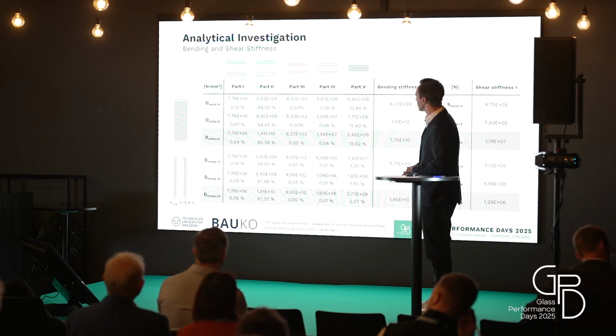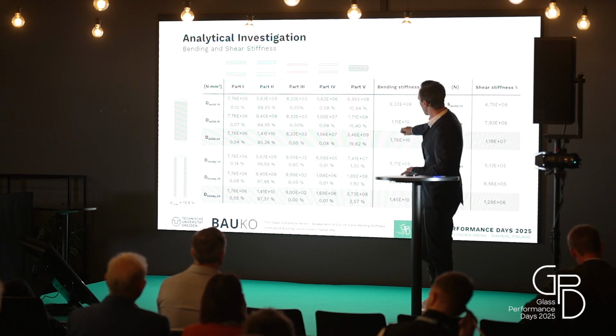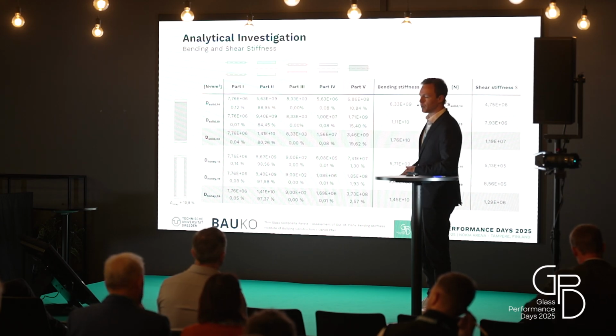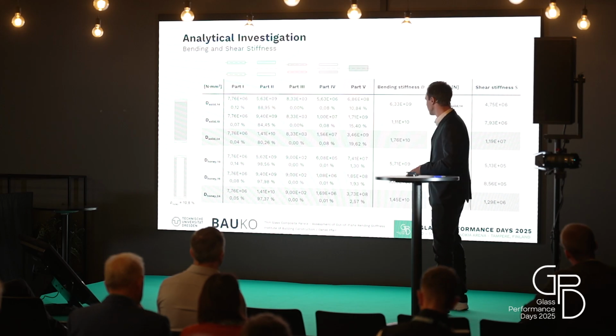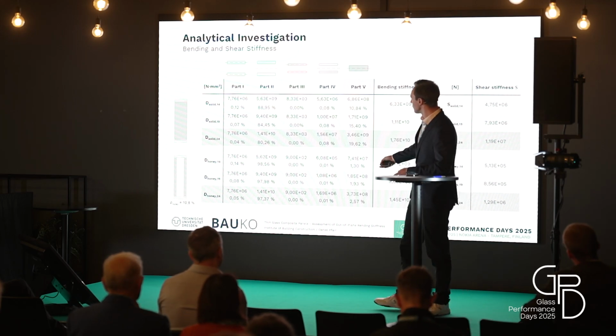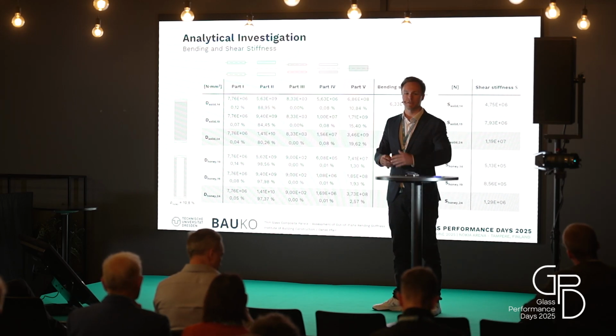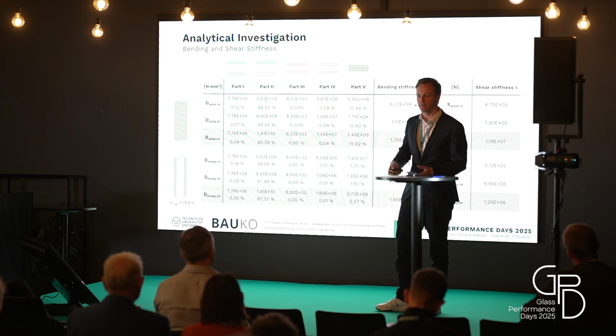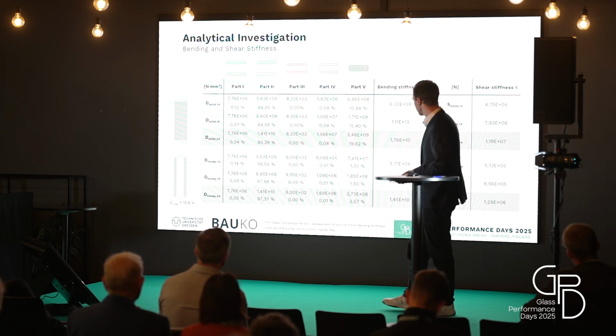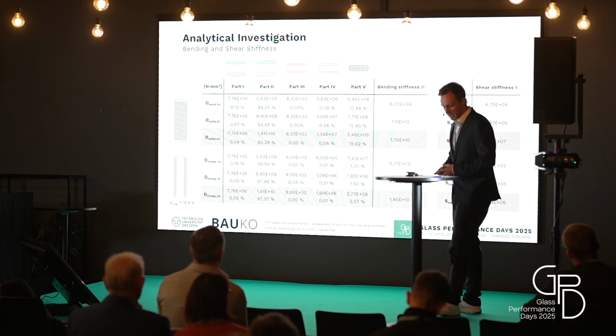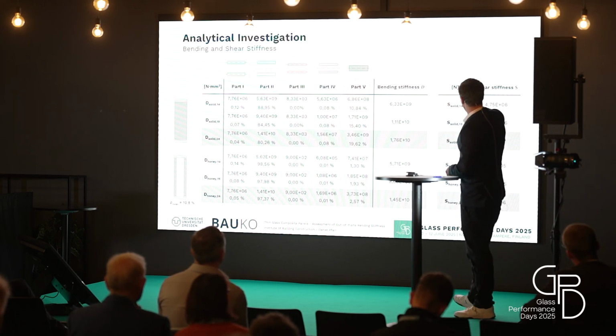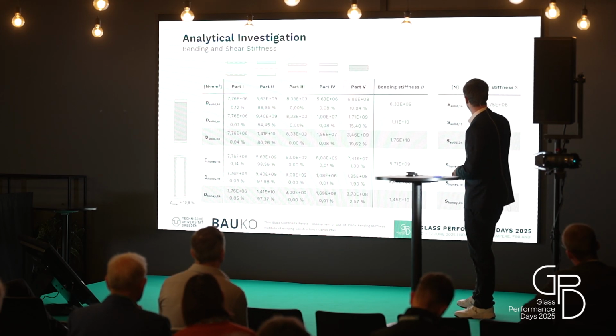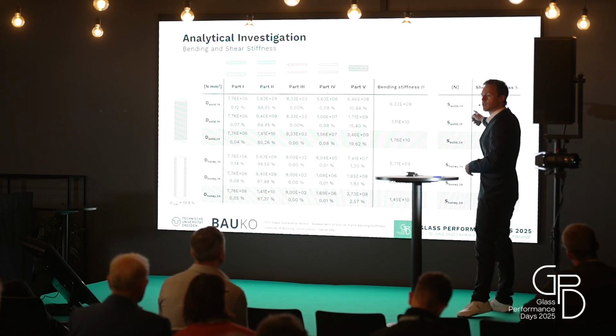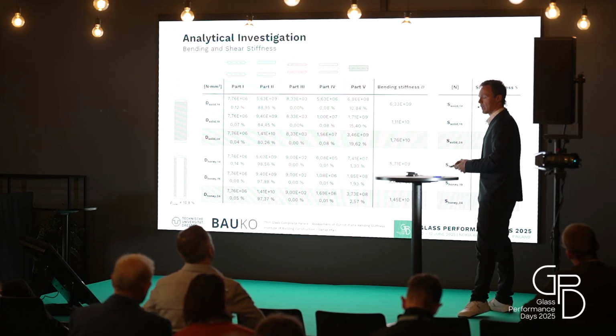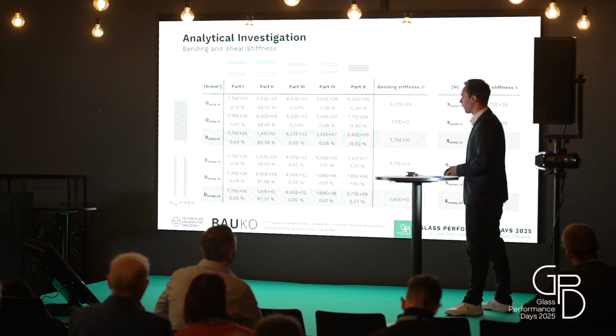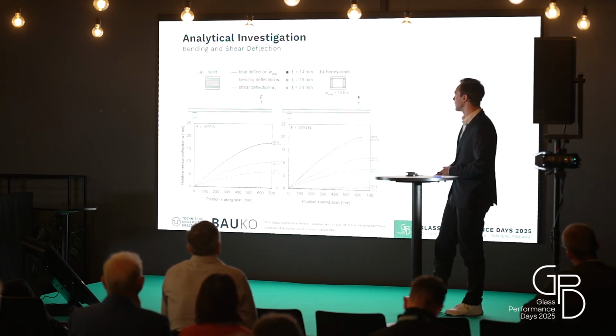And if we look into the honeycomb, then we can see this amount of bending stiffness for the core is decreasing to around 1 to, let's say, 3%, and so the major part is really covered by the face sheets. That is very well known as the sandwich effect. The shear stiffness as well, here in that case it's only one component, but comparing the solid against the honeycomb, we have a huge difference in shear stiffness, so we can expect a higher amount of shear deflection, which we can look at right now.